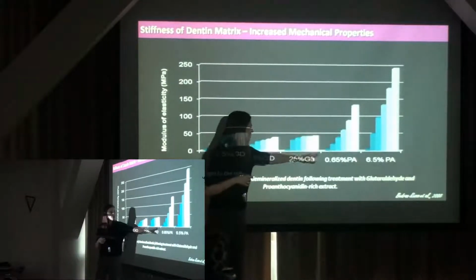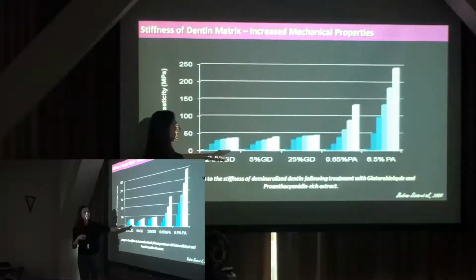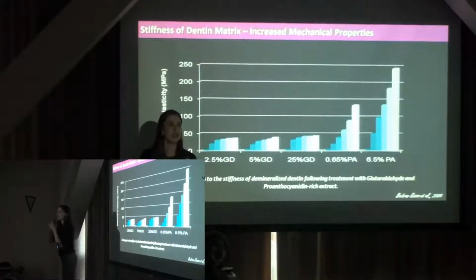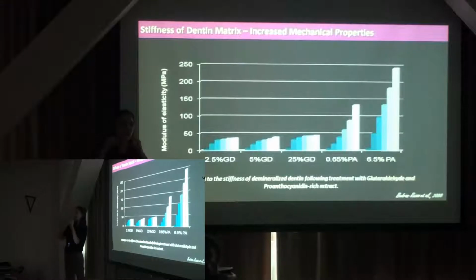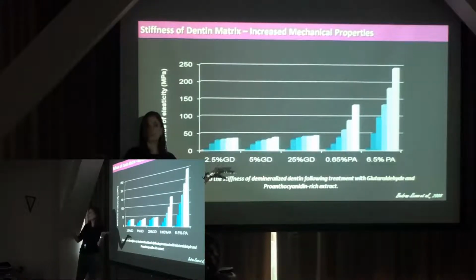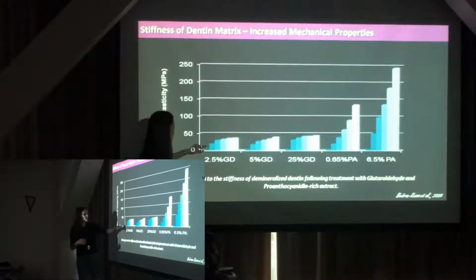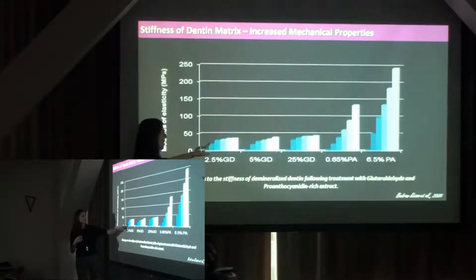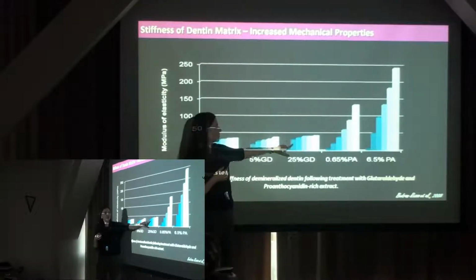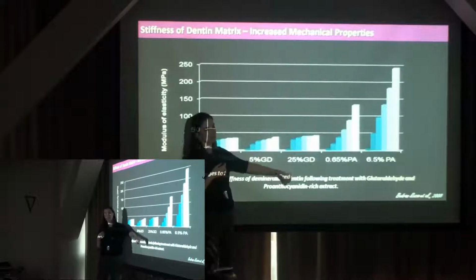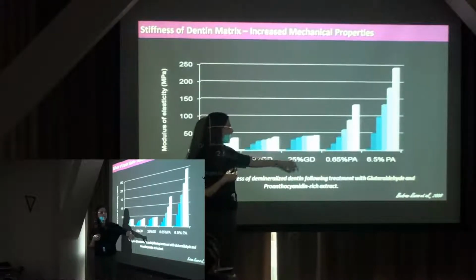And that's a specific characteristic of glutaraldehyde because it needs these free amino groups in the collagen. Once they use them all, there's no other mechanism by which it cross-links. So the difference in concentration is just how quick the initial reaction takes place. So it can be as quick as 10 minutes. You would get pretty good results.